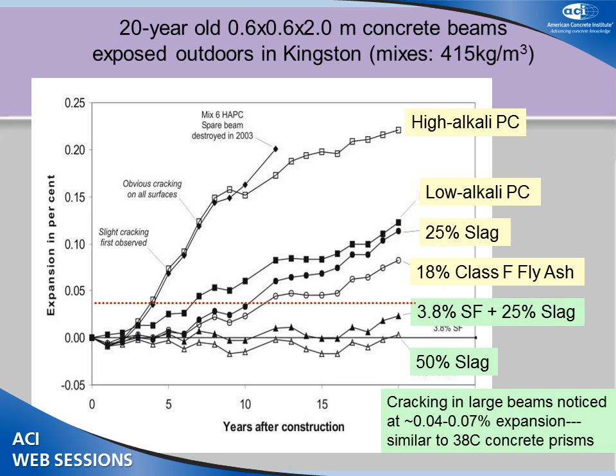We're seeing this in the field in Canada, which is not the hottest environment compared to places like the Texas site. So what you see, we had a pair of identical beams. The 2 lines going up the highest there, where we had a redundant beam, and we can see that the expansions, the 2 beams expanded pretty much exactly the same. One of them was sacrificed to do some work on RCA that Medhat Shihada did after about 12 years.